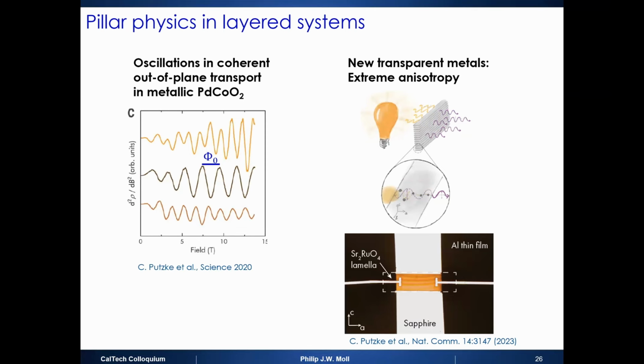So if you now linearly polarize an electric field, such that of light, such that it points perpendicular to these planes, you can look through this. And so you can have all of these, for example, strontium-ruthenate or cuprates, and you can look at them while they go superconducting with cuprates. The strontium-ruthenate may be harder, but with cuprates, you put them in nitrogen and you watch them go superconducting. They're brownish in this limit. It's very interesting. They are record transparent conductors. They blow ITO out of the water.